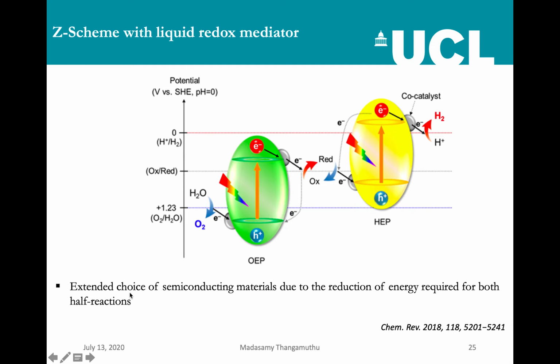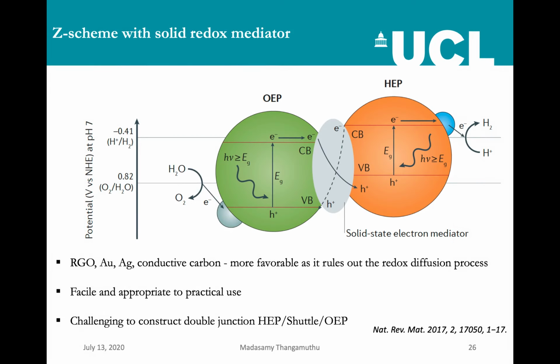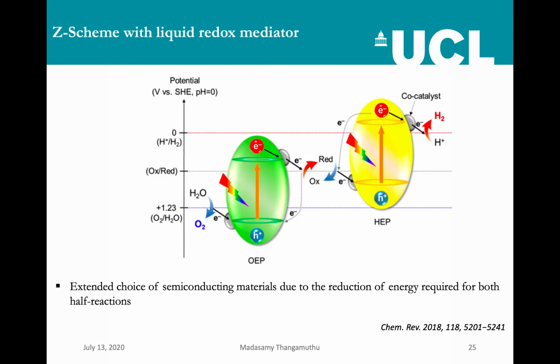So as there are a lot of semiconducting materials, narrowband semiconducting materials one can use in such a Z scheme system. So in the previous Z scheme that I explained, we use liquid redox mediator. So, you can see, let's say if I take the Fe3+/Fe2+ redox system, this can consume the holes from the hydrogen evolution photocatalyst and electrons from the oxygen evolution photocatalyst.